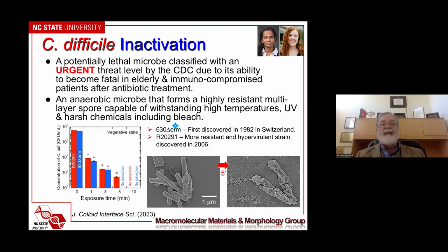Well, we looked at 2 different strains, one which was hypervirulent, and we found that between 5 and 10 minutes, we were able to completely inactivate the vegetative state of C. difficile. This is where it becomes contagious, and we actually got more than 6 log units reduction. And these are the SEM images, and once again, we see only the husks from the outer membrane remaining.